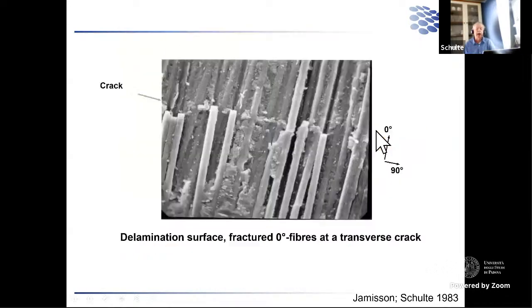So that means we had to damage a part, to bring it to failure, to crack it, and then you see here a failure surface of a delaminated area of a transverse crack. And what we can see here is a crack line, the tip of a crack line that goes from the left to the right, a little bit below, and near the tip of this crack line, there we could see fiber fracture, but that there occurs a fiber fracture, we could only see after a total damage.